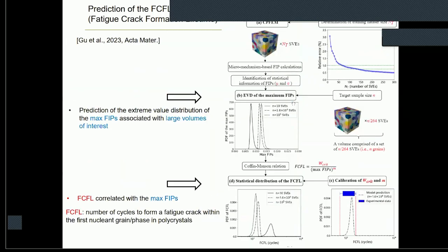And then in another work, we carry out some simulations using crystal plasticity models. So we collect the statistical information of FIPs. We already talked about the way to predict the maximum value of the FIPs in terms of the sample size. You can see that it is right-shifted with a larger number of grains accounted for. And then I use a typical way, the so-called Coffin-Manson relation, to build up a link between the fatigue crack formation lifetime and the maximum value of the FIPs. In this way, we can directly predict the fatigue lifetime in terms of the number of grains accounted for.